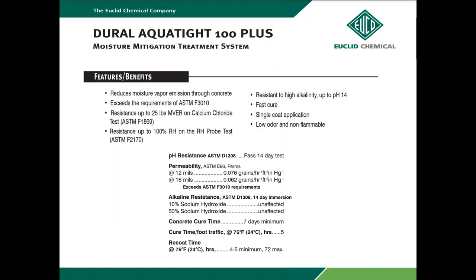So this is just one of our moisture mitigating coating systems. You can see its resistance is up to 25 pounds per 1,000 square foot, whereas typically your limit is 3 pounds in a concrete surface for most of your moisture sensitive flooring. We can apply this material if moisture levels are as high as 25 pounds per 1,000 square foot. We can apply it to concrete with a relative humidity of 100%. And at that point, it stops all moisture from coming up through the concrete slab.